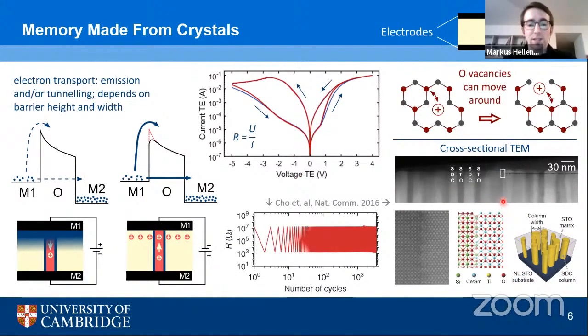Resistance is just the voltage divided by the current. So if we take some arbitrary voltage here, either we divide it by the larger current or by the smaller current, and this means we get 2 different resistances. This is sketched out in the figure down here from the same paper as these images. So we see that the resistance switches between 2 distinct states, a very high resistance and a low resistance, and we can switch between these states back and forth thousands and thousands of times.